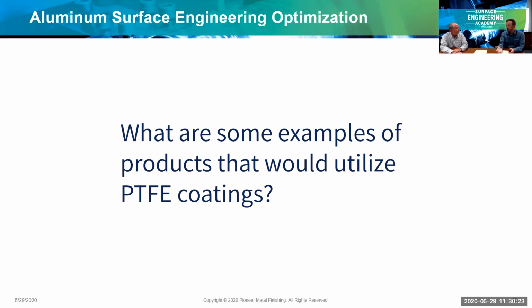Yeah, so think about applications though, high cycle, metal to metal type contact, whether that be surface friction, surface wear, anti-galling. And really the lubricity factor serves as a force multiplier for hardness in the wear resistance equation. We see advantages not only of having a hard coating, but also a slippery coating. That's your best wear resistance, is that combination. So metal to metal scenarios, and not even both metals needing to be aluminum, perhaps a steel and aluminum interface where you'd want to protect that softer aluminum.